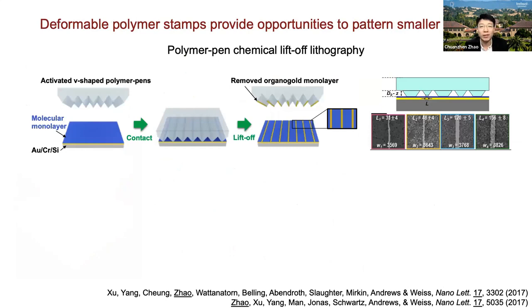The first thing we explored is to take advantage of the soft nature of soft lithography. The reason it is called soft lithography in the first place is because we use softer stamps, the PDMS stamps, for the patterning. Soft means they are deformable, that they will change their shape upon applied force. We first demonstrated a polymer pen chemical lift lithography, where the PDMS probes were made by those V-shaped stamps, and we designed the polymer pen with different features, as we can use those big ones, as we show here, as a supporting arm, and the smaller ones to produce small features.